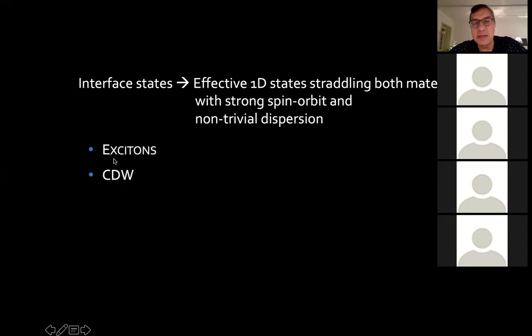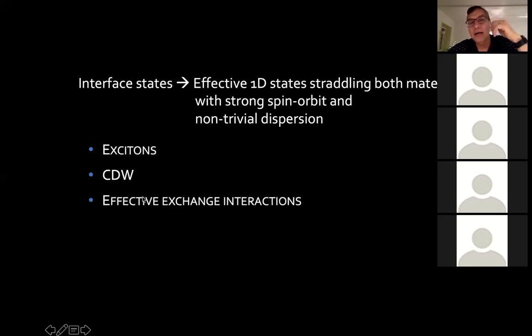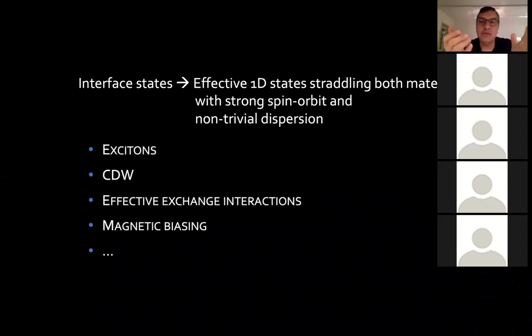But the other thing is that because you can dope this material so that the Fermi level is right where these gap states occur, you can imagine that you'll have charge density waves. So it's a 1D metal essentially. And so there will be a strong interaction effect. There will also be, if you put magnetic impurities close to these interfaces, effective exchange interactions between these magnetic impurities. You can imagine magnetically biasing these edges or interfaces, and a number of other interesting interaction effects, all right? Which will include interaction in a strong spin orbit.